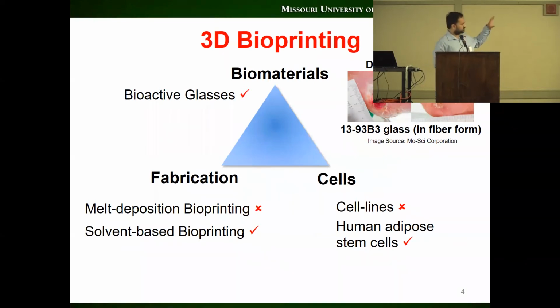So there are three important aspects in bioprinting. One is the materials, the fabrication process itself, and then cells. In materials, Julie just talked about the borate bioactive glass. We have Mo-Sci Corporation and today. So we use bioactive glass, borate bioactive glass. And for the cells, we use adipose stem cells with Julie in her lab. And then the process: the commercial bioprinting processes are mostly melt deposition bioprinting, where we use heat to melt the polymer. But the problem is it has high temperature, so we use a novel process called solvent-based bioprinting.